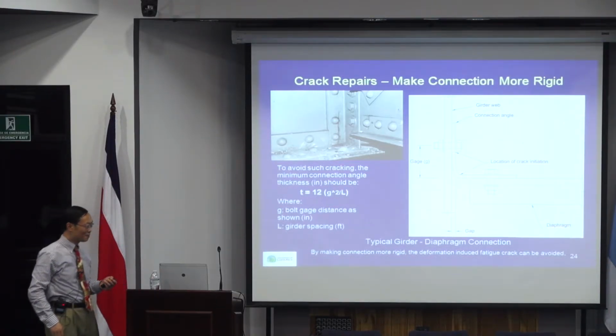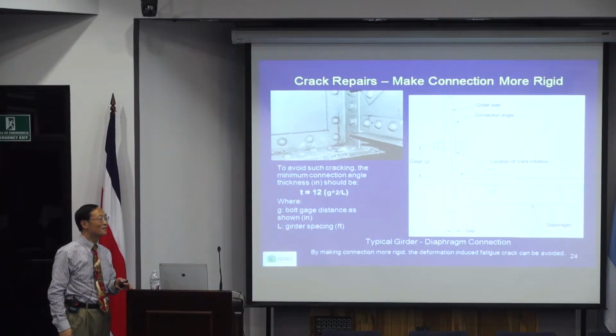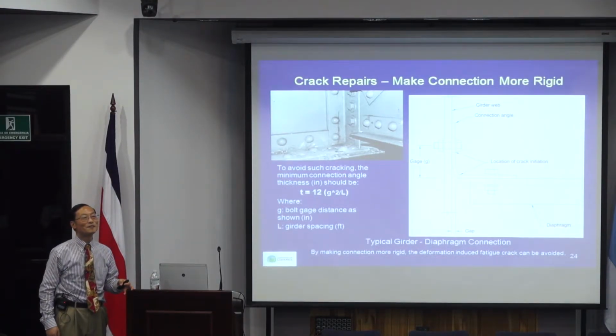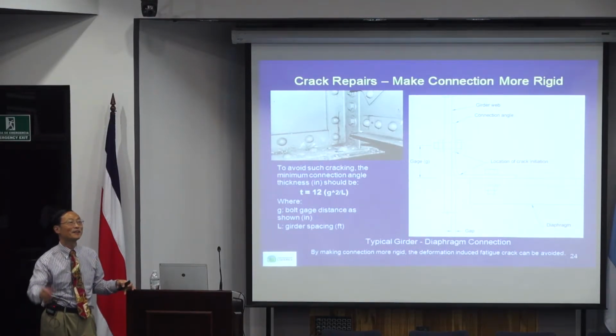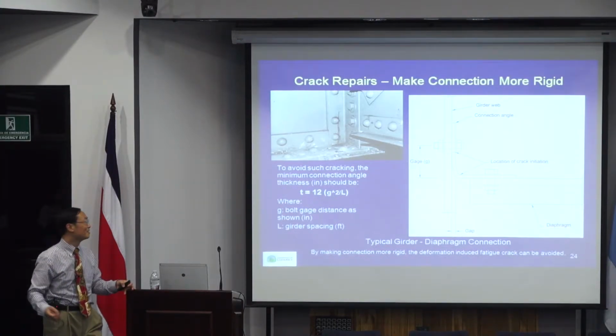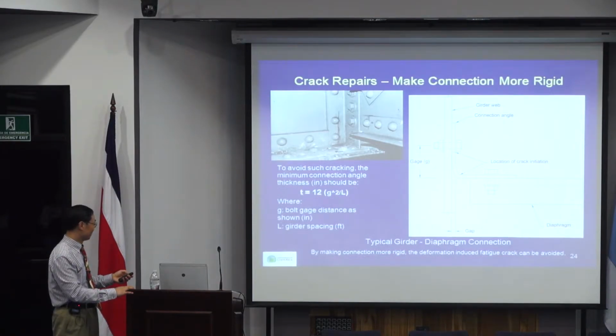A lot of fatigue cracks are not caused by stress. Of course, stress is something we discuss most because we know how to calculate it. But more than 50% of fatigue cracks are caused by uncontrolled deformation. For example, if you have a member connected to that, and that is a diaphragm member, the diaphragm has tension and compression force, so that causes that member to deform. That's why it causes cracks there. That is extremely difficult to quantify. So all you can do is provide a member with sufficient thickness, or just avoid this kind of detail altogether.